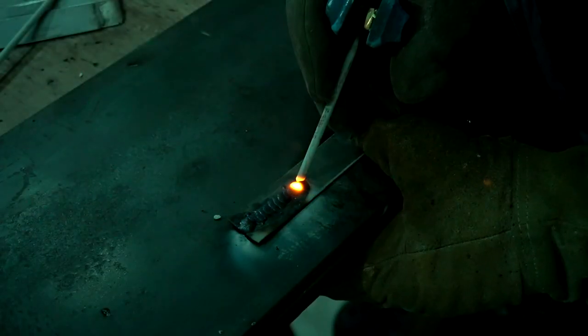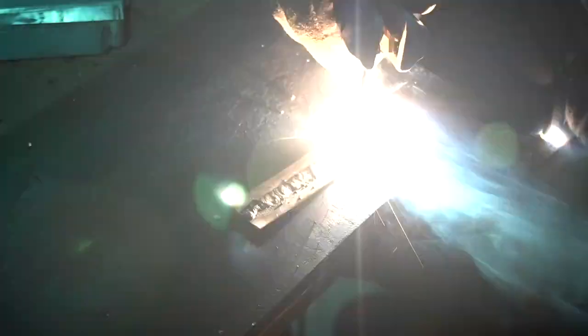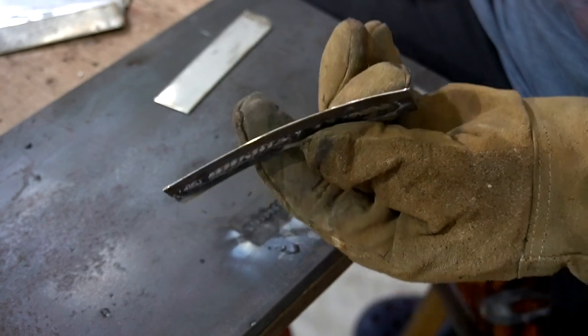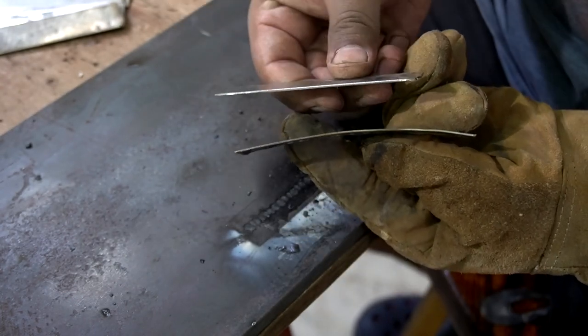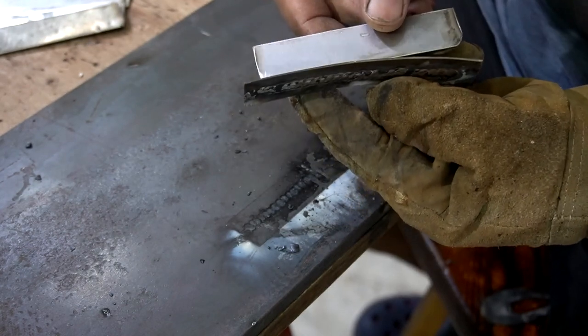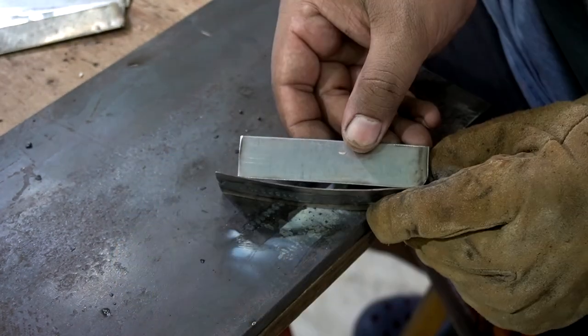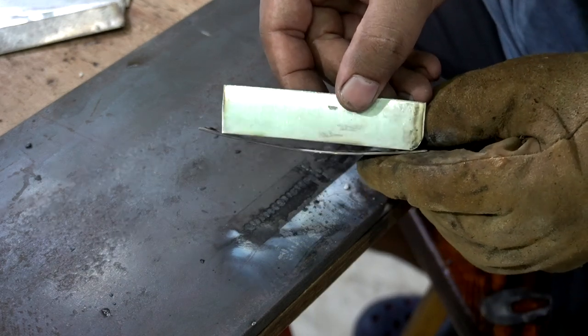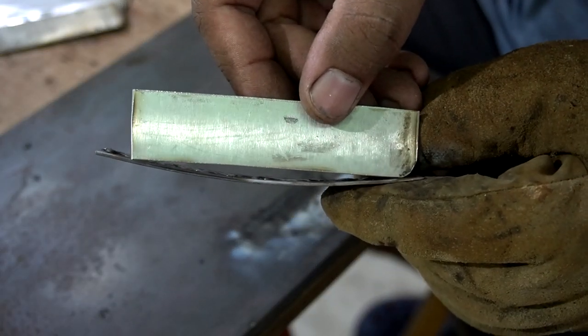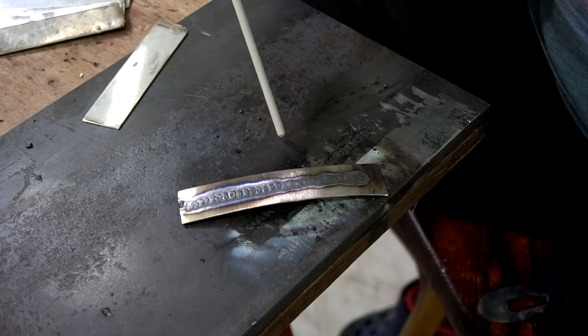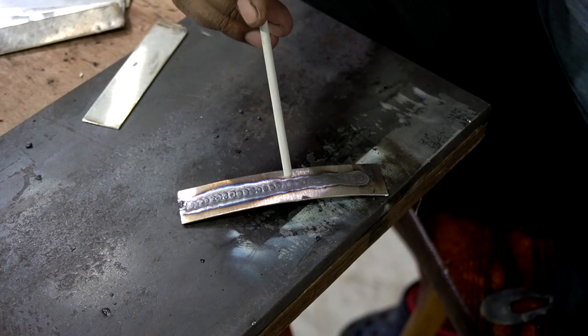In that case, you are always able to succeed and able to avoid the blowholes formation onto the base metal. During the welding you can clearly see that the material starts to warp, and this is because the weld, when it cools down, tries to contract, and that's the reason behind that. And you can see how much this strip is going to warp, and surely you are able to avoid this by clamping your workpiece. And at the back side you can clearly see the impression of those weld beads,